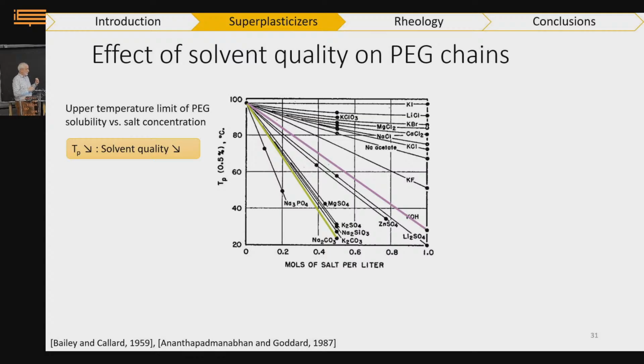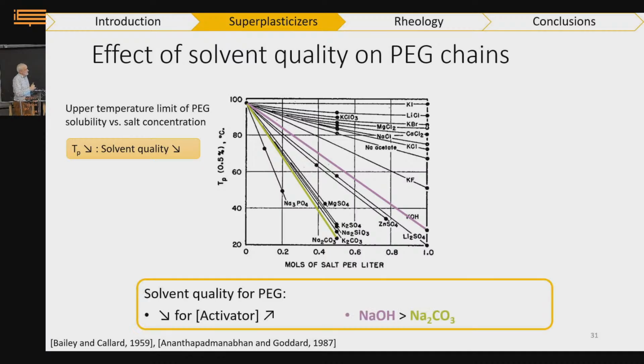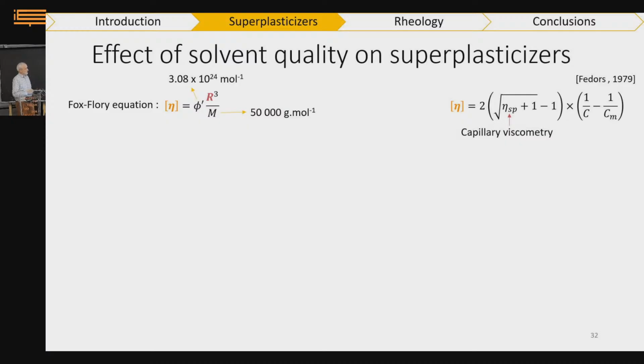But the first message was that solubility of the polymer depends on salt concentration. And the second message is that it depends on the anion, with a series that is very similar to the Hofmeister series. Meaning that, for instance, with sodium, you see the solubility is degraded much slower with hydroxide than with carbonates. So we know that the solubility of PEG is degraded when we put hydroxide in solutions, which is what we do to activate the system. And it's going to be worse with carbonate, but let's wait for that. Let's just talk about the hydroxides for the time being.